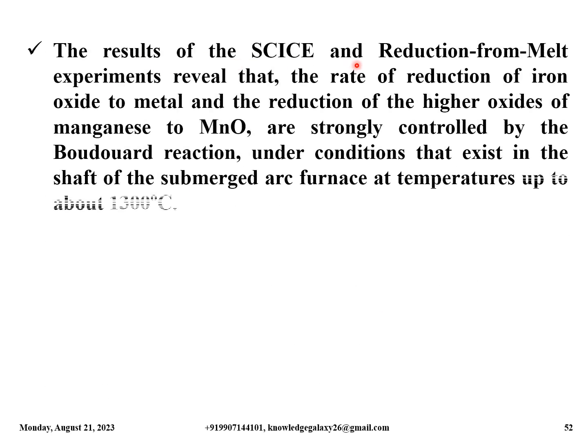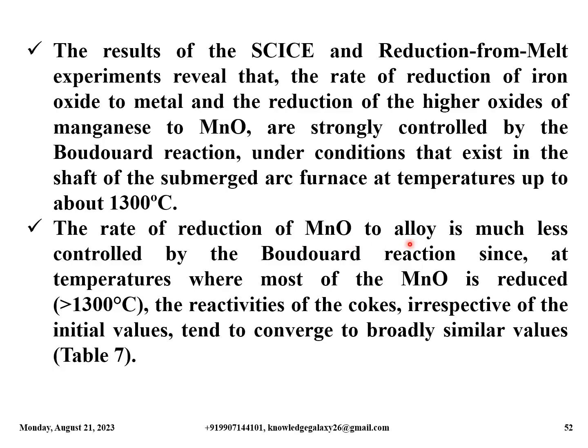The results of the SCICE and Reduction-from-Melt experiments reveal that the rate of reduction of iron oxide to metal and the reduction of the higher oxides of manganese to MnO are strongly controlled by the Boudouard reaction under conditions that exist in the shaft of the submerged arc furnace at temperatures up to about 1300 degrees Celsius. The rate of reduction of MnO to alloy is much less controlled by the Boudouard reaction, since at temperatures where most of the MnO is reduced, that is above 1300 degrees Celsius, the reactivities of the coke, irrespective of the initial values, tend to converge to broadly similar values as shown in table 7.